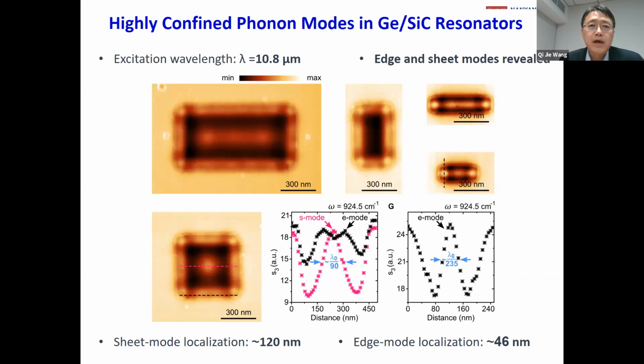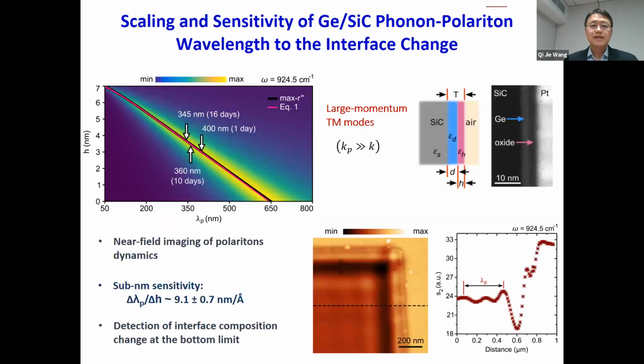And such edge mode can have high momentum, higher than that of the sheet mode. And therefore, if we measure the confinement factor, as shown in this figure on the top, in the middle, okay, we can see the confinement can reach beyond 200. So such a system gives a very high confinement of the edge mode, with a spot size down to around 50 nanometers. And we further investigate the sensitivity of this germanium silicon carbide Phonon-Polariton wavelength to the change of the interface compositions.